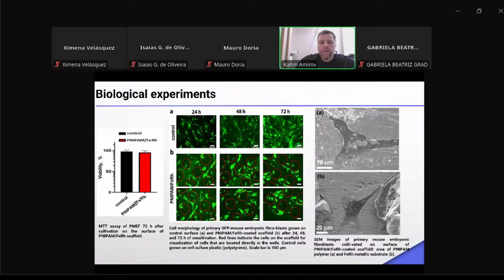And as you can see, the biological experiment shows that the material has low toxicity, but anyway, more biological experiments are needed. And we also made some images of this composite, and as you can see, the fibroblasts fill the wells, they attach on polymer, it's figure A, and as well on the metallic part of iron rhodium, because as I noted, the polymer does not fully cover the surface of metallic substrates due to the imperfectness of wells after laser treatment.